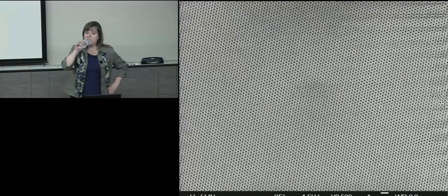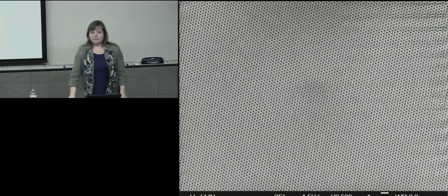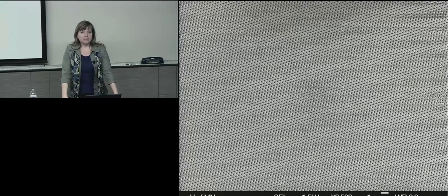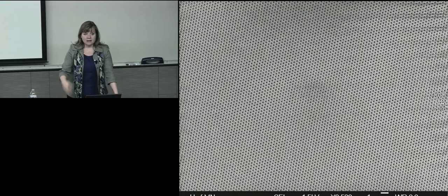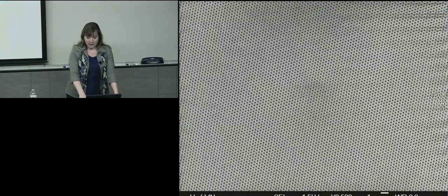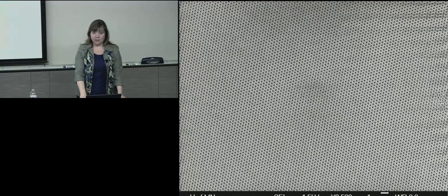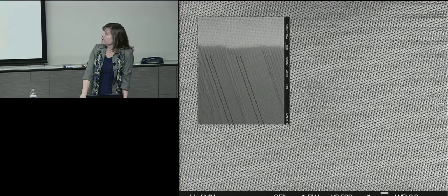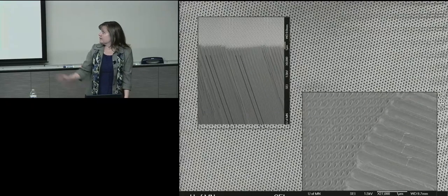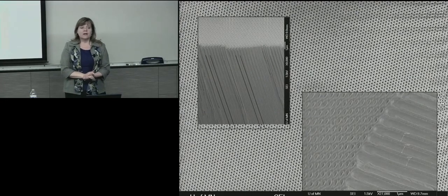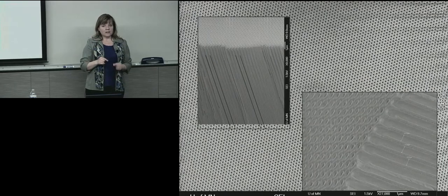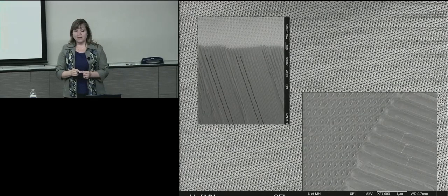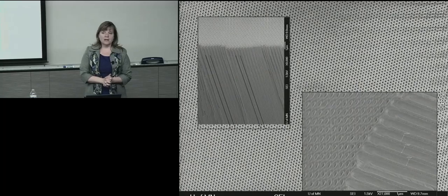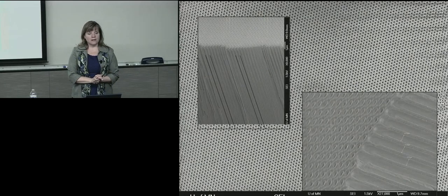How do you make the stamp? You have to have a mold or something to stamp it? Yeah, so we use e-beam lithography for that. Actually it's a very good question because this is my next point, is that initial stamp costs a lot of money. And let me just show you what the pores look like up close, and we'll talk about that. Okay, there's the sidewalls, and that's the other, the straight sidewalls. All right, so this stamp was 1 millimeter by 1 millimeter. And back maybe 10 years ago, it cost something like $1,000.